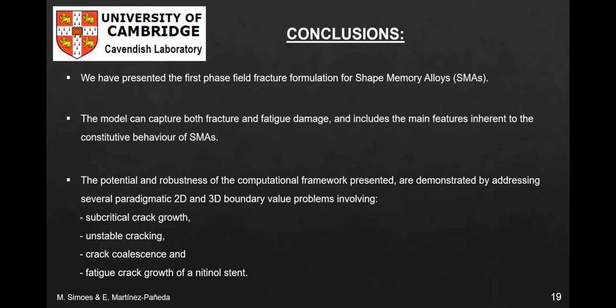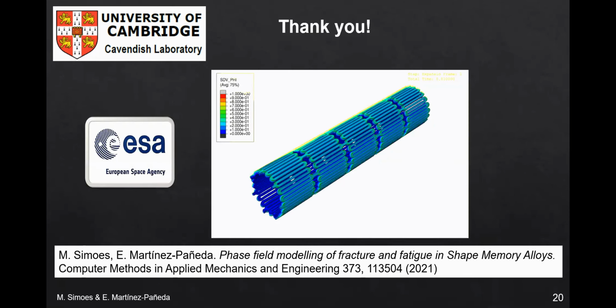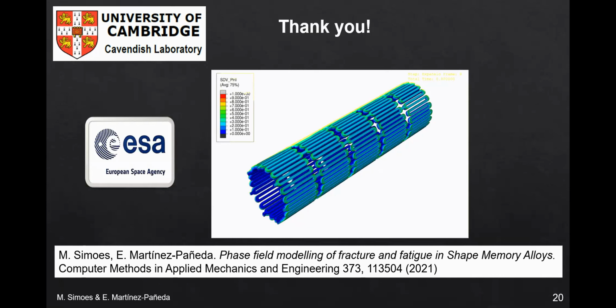So I will conclude by saying that we have presented the first phase field fracture formulation for shape memory alloys. The model can capture both fracture and fatigue damage and includes the main features inherent to the constitutive behavior of shape memory alloys. We have demonstrated the potential and the robustness of the computational framework by addressing several paradigmatic 2D and 3D boundary value problems involving subcritical crack growth, unstable cracking, crack coalescence, and fatigue crack growth of a nitinol stent.